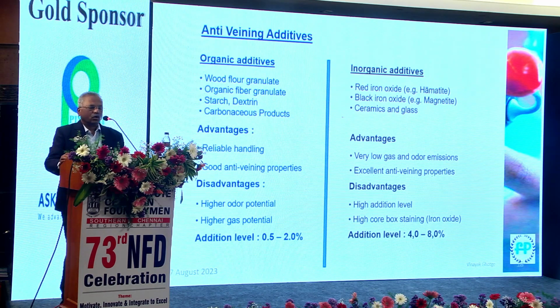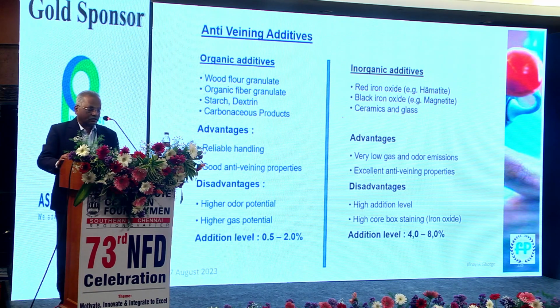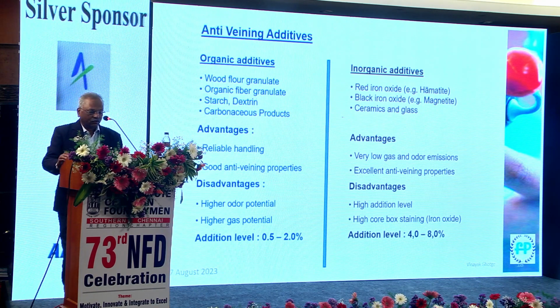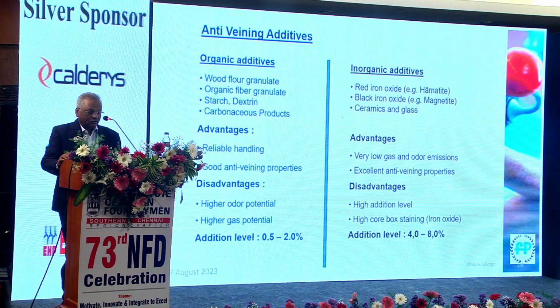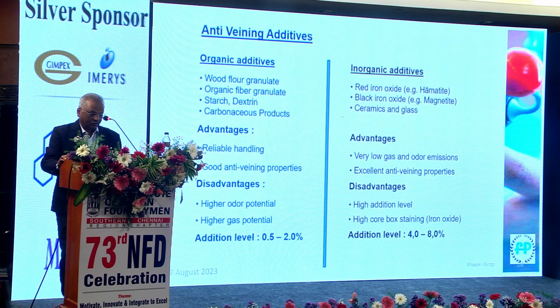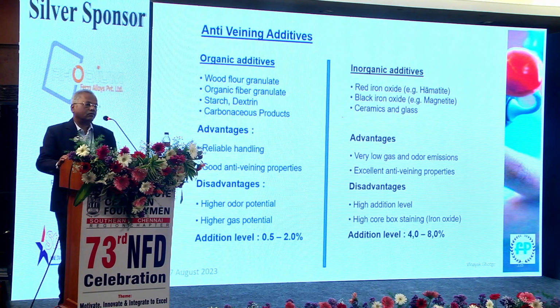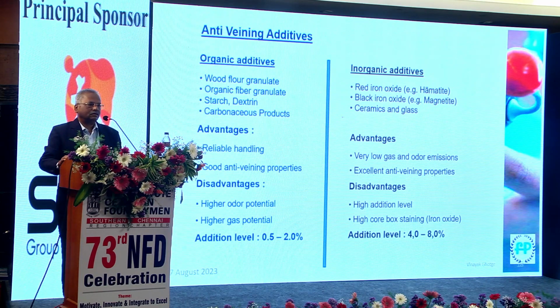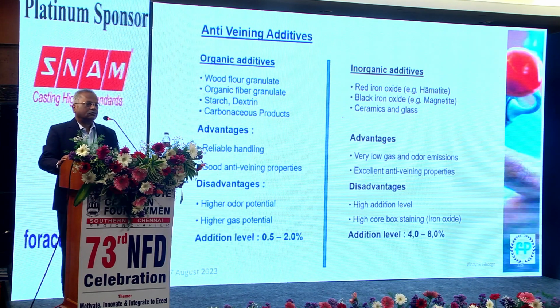This is the broad comparison between organic and inorganic additives. Organic additives like wood flour, fiber granulate, starch, dextrine or carbonaceous products are reliable in handling and have good anti-veining properties, but the main problem with this is high gases involved. Although the addition rates are quite controlled, between 0.5 to 2%, they evolve a lot of gases, and hence it is difficult to use organic anti-veining compounds in critical core areas where the core thicknesses are quite low.